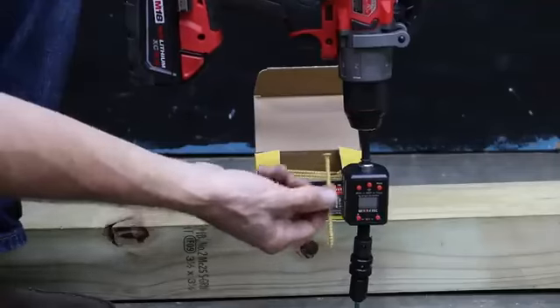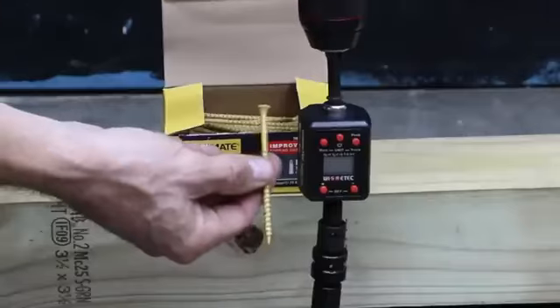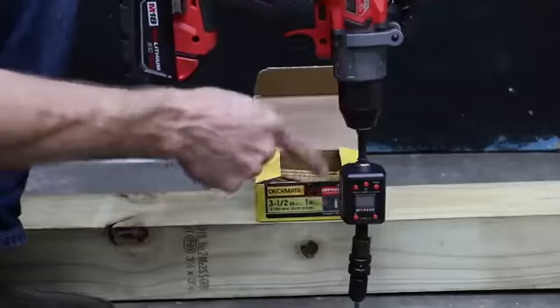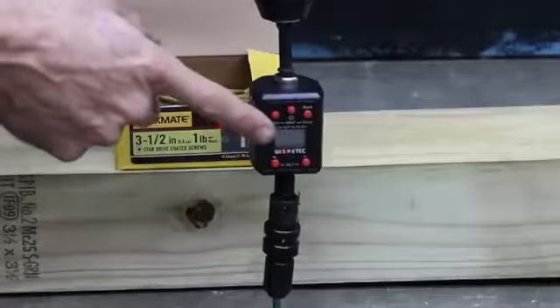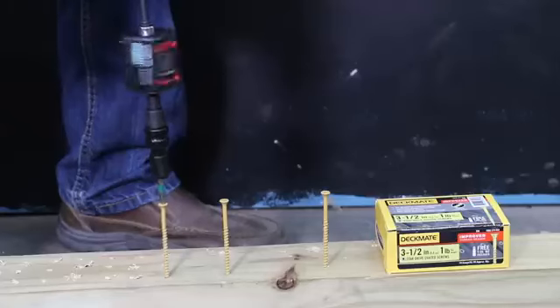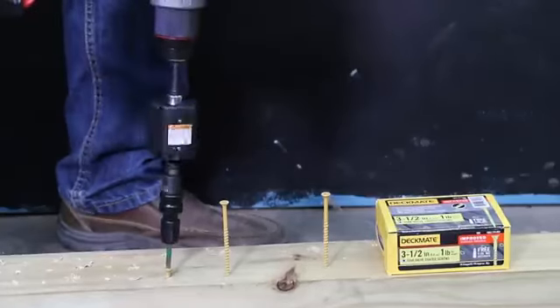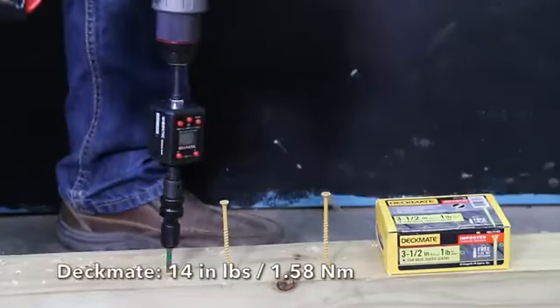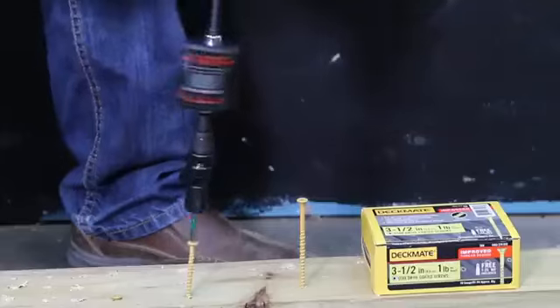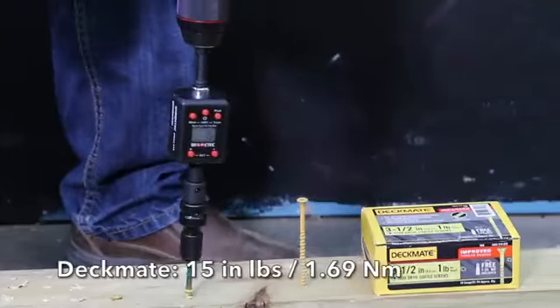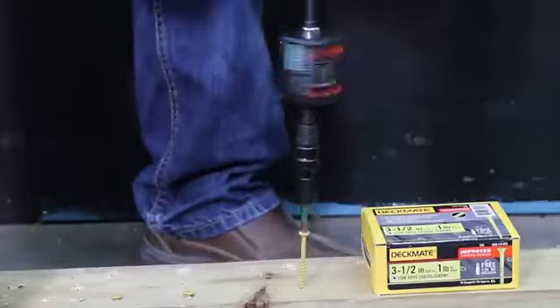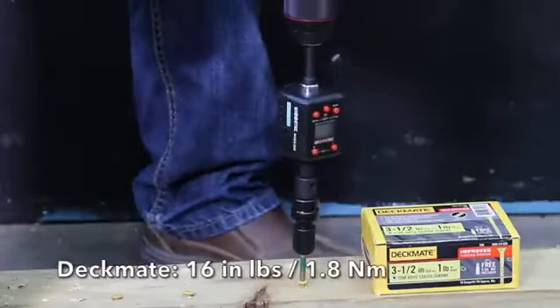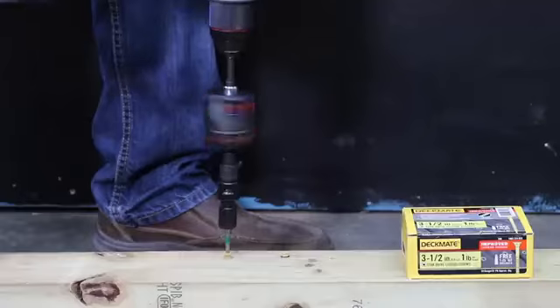Since several of the brands claim to be easier to drive than the competition, let's drive in 3 screws to see which requires the least amount of torque. The inline torque adapter will keep track of the maximum torque. The first Deckmate screw went into the pressure-treated 4x4 without requiring too much torque at 14 inch-pounds. The second screw performed nearly the same as the first at 15 inch-pounds, or 1 inch-pound more than the first. And the third Deckmate screw performed nearly the same as the first two, 16 inch-pounds. So 15 inch-pounds on average.